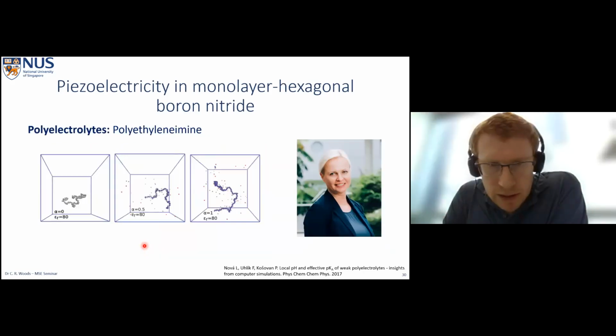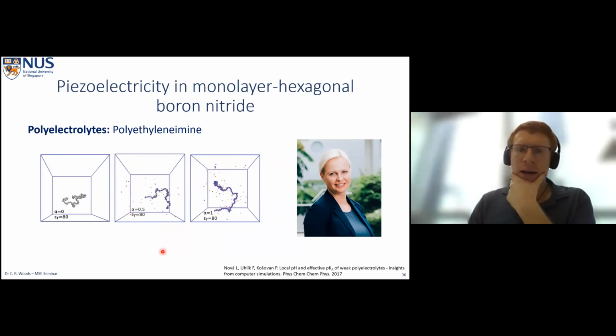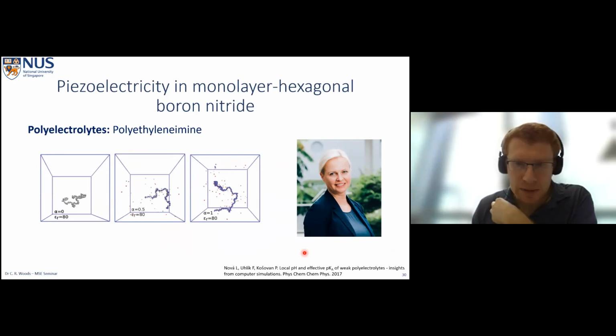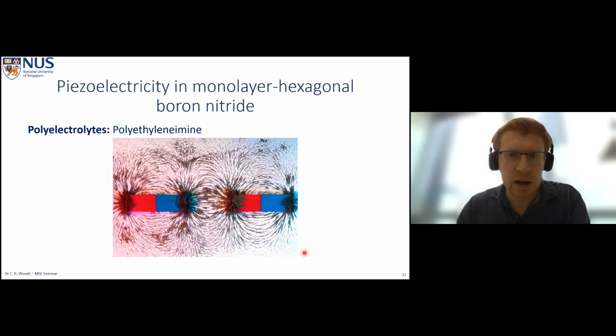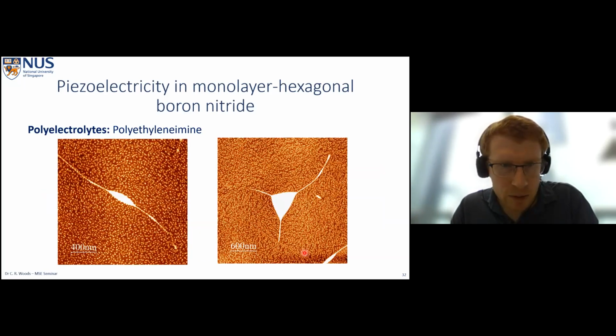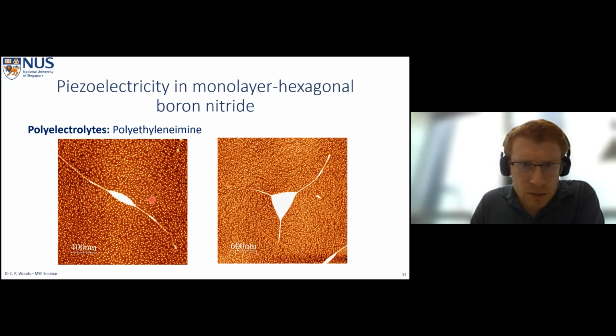So Dr. Andreeva had the smart idea of maybe trying to deliberately introduce some polymer onto our sample, but using polyelectrolytes. And these PEI polymers are long polymers which tend to align along electric fields. So they can feel an electric field and they want to align upon the electric field. And so we could put them on our sample, and what we would hope is that we would see something like, you know, when you put iron filings on a magnet and they follow the magnetic field lines, something like this in our sample. So we did this, and we got these very nice, very beautiful images where you can see some kind of correlation in the direction of our polymers as they interact with the bubbles in the center of our picture.